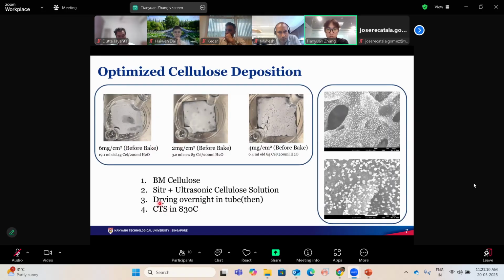We used drying in the tube instead of just the filtration, like the reference paper mentioned, and we found that the cellulose was better distributed on the carbon paper than with our original method. And we can see the right SEM picture too. The copper nanoparticles are distributed more uniformly, and the numbers increased a lot with this deposition method.